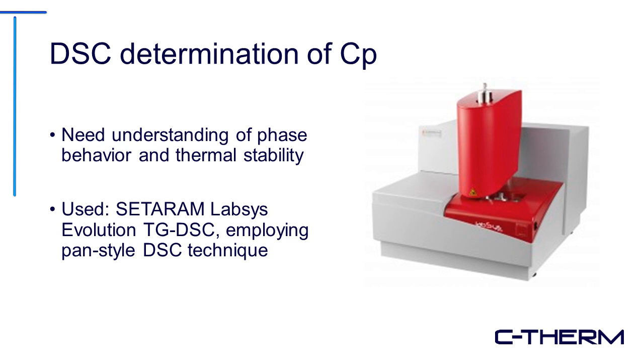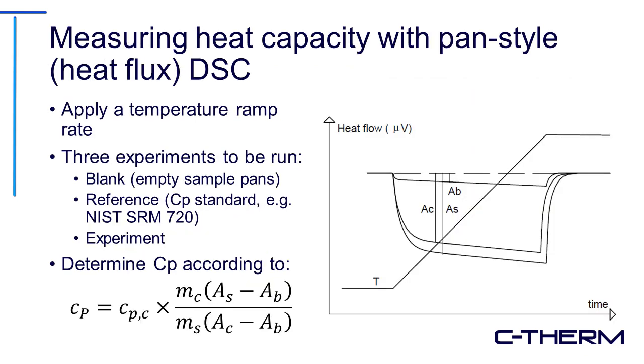Now, what's really important when you're looking at the thermal effects of titanium or any types of additive manufacturing powders is being consistent between batches. The effects and the strain and the physical properties of each of these manufactured parts can dramatically change based on the physical properties of the powder that you're using. So it's important for manufacturers to make sure that these are consistent between batches. And one way we can do this is, as we've shown today, through thermal conductivity, but also through the characterization using CP, or heat capacity. So it's typically very easy for us to do this.